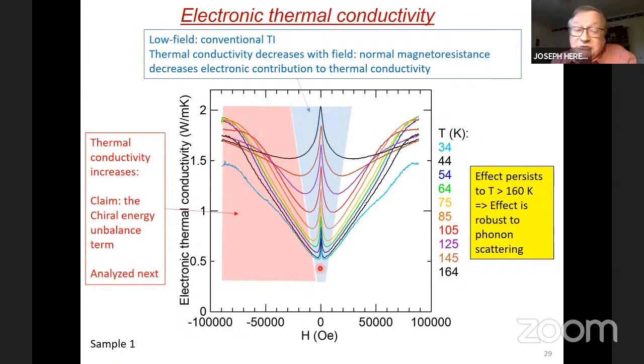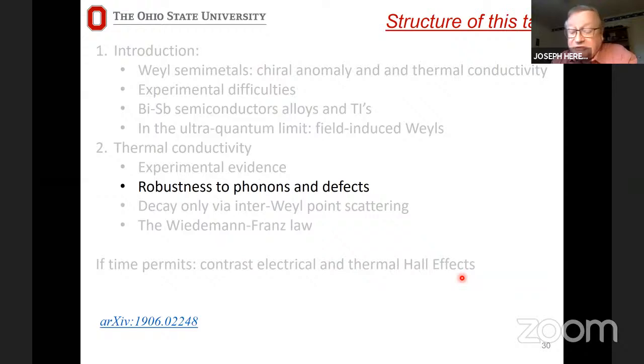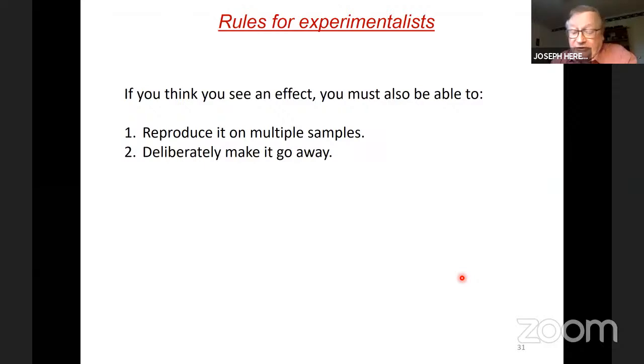When we get to the ultra quantum regime, that is when we clearly have an increase in thermal conductivity with magnetic field, which we claim is the effect of this chiral energy imbalance term that I explained in the beginning of my talk. Notice, of course, that 160 Kelvin and certainly 200 Kelvin is much higher than the Debye temperature, which is around 100 Kelvin. So we claim that this effect is actually quite insensitive to phonons.